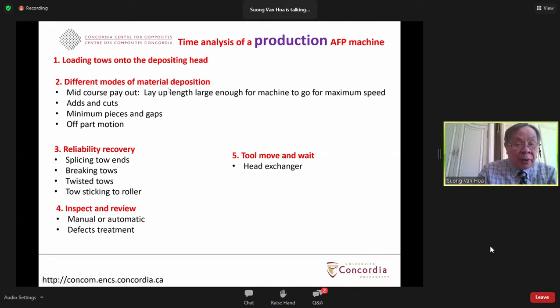I mean, during the time that you deposit the material, it depends on whether you have a continuous course of the machine running that can go very high speed, they call it the mid-course payout. Or you have some kind of a location where you have to slow down, where you have to add or cut the tows. Or you have a small piece with a gap. And another motion here called the off part motion. That means when the machine had to go back from the beginning to lay down again, so they get off away from the surface of the part. So that's an off part motion.